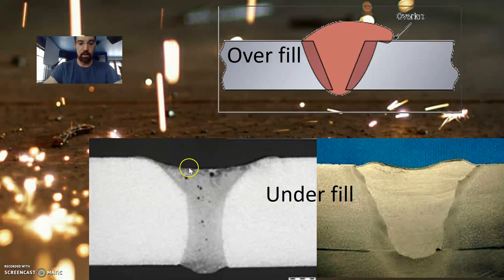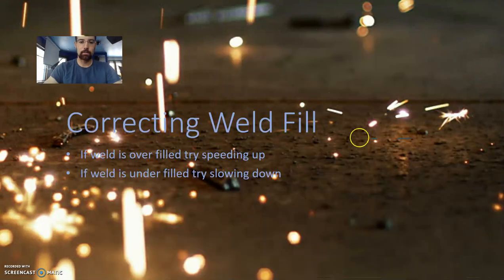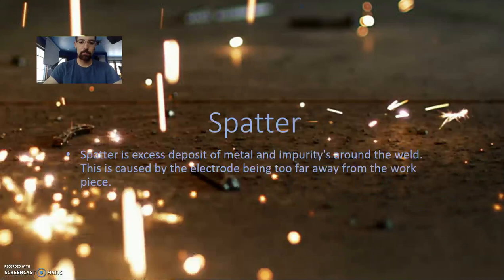The X-ray on the left has some porosity in it. You can see little black spots. In the picture on the right, you can see this concave effect on both of them. That's underfill. You really want your weld to be about a sixteenth to an eighth above the surface of the weld. That way you can grind it back out and have a nice flat surface to work with. So correcting weld fill, again, it's just going to be your speed. If you've got too much fill, go a little bit faster, and if you've got not enough fill, go a little bit slower. It's just going to take some time to play with that.